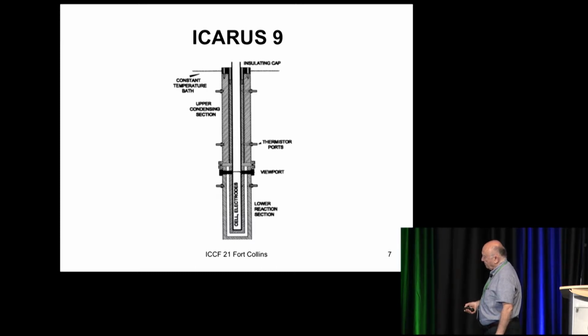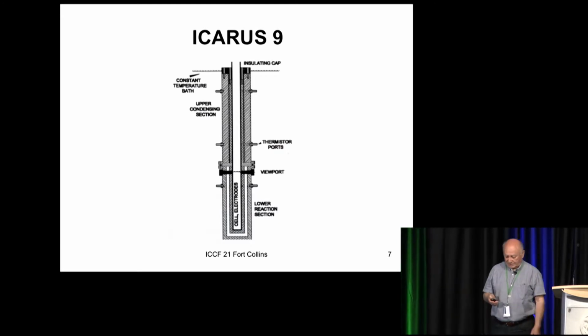So by measuring all these temperatures, and depending on the power that's available, you will be sensitive to low level here, medium level here, and high level here. And depending on the quality of this insulation, you can run it at various powers. Obviously, if the power is too high, at one point the vapor will go away. But the good thing with this system is that you can have continuous boiling experiments, because I realized there was more excess heat at the boiling level than at lower temperatures.